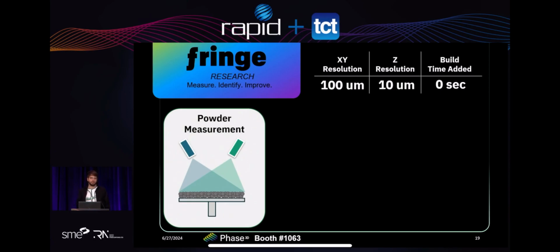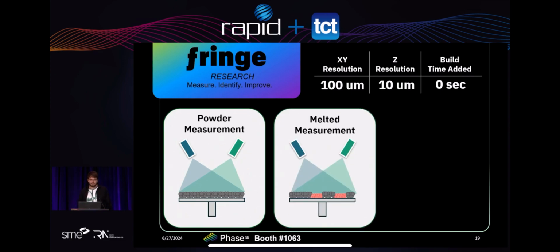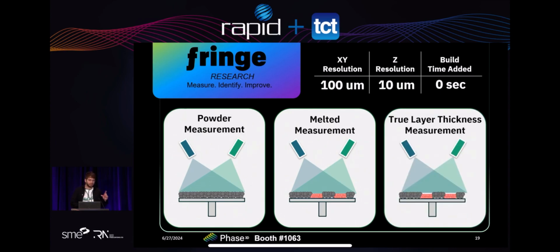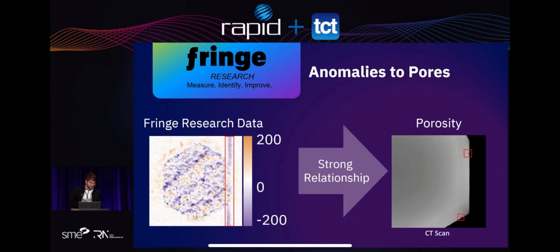We take a height map of every layer several times per layer, and we report analytics using that point cloud of data. The first scan we do is after the powder is spread. We take a powder measurement. Then after the material is melted, we take a melted measurement, height map. And then we take a third measurement so we can look at the powder layer thickness that's spread across the part, as well as how the part areas are melted down lower into the build. And what we're really excited to share is that we've witnessed a very strong relationship with our Fringe Research data in situ and porosity formation that we've detected using a CT scan.